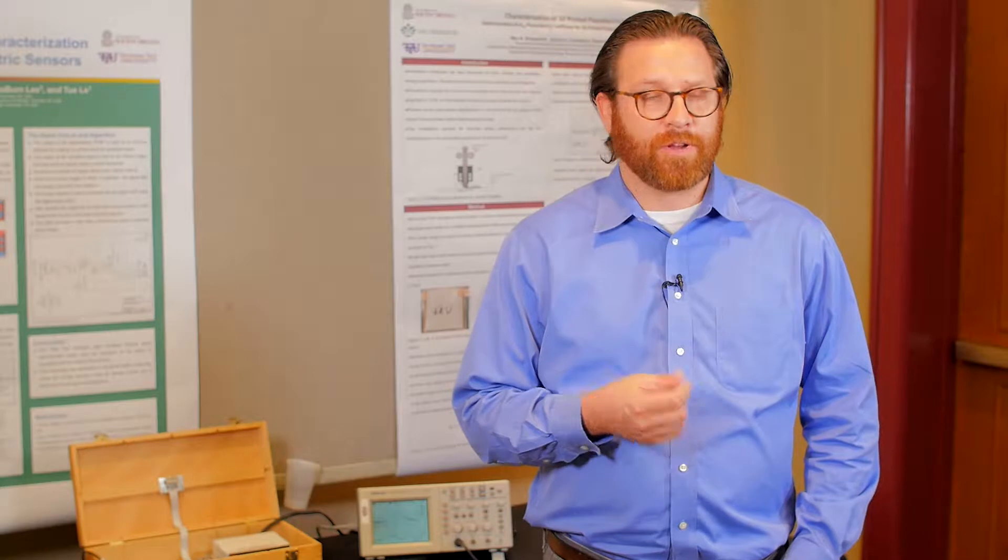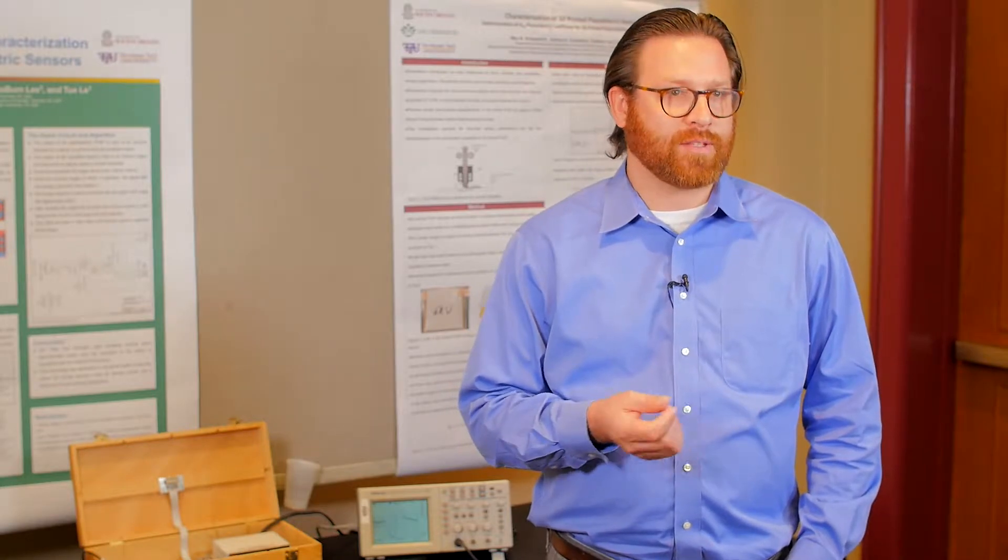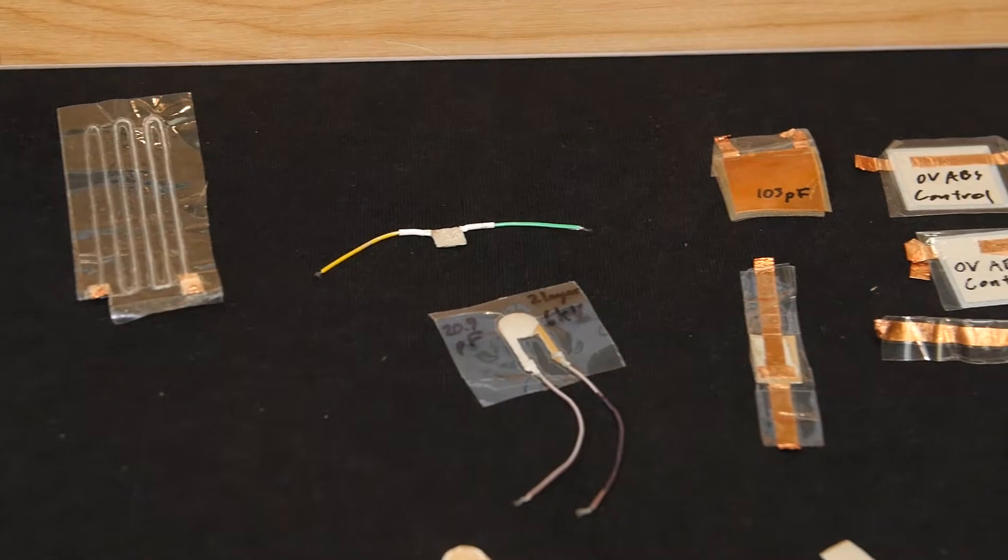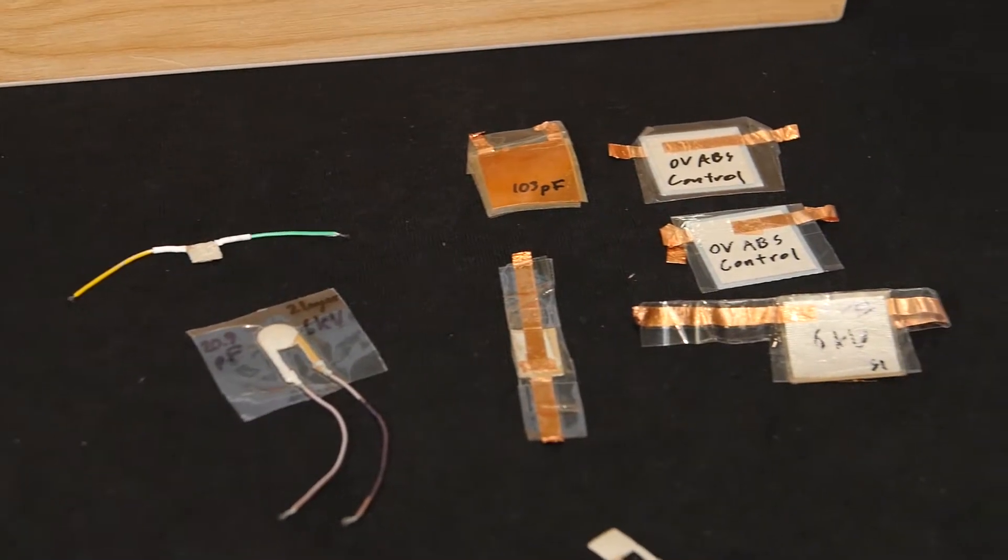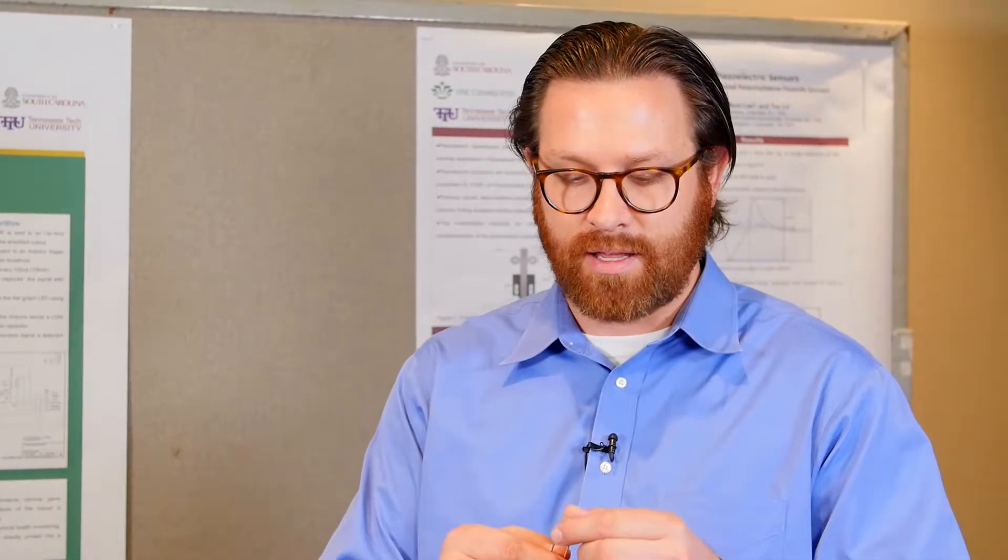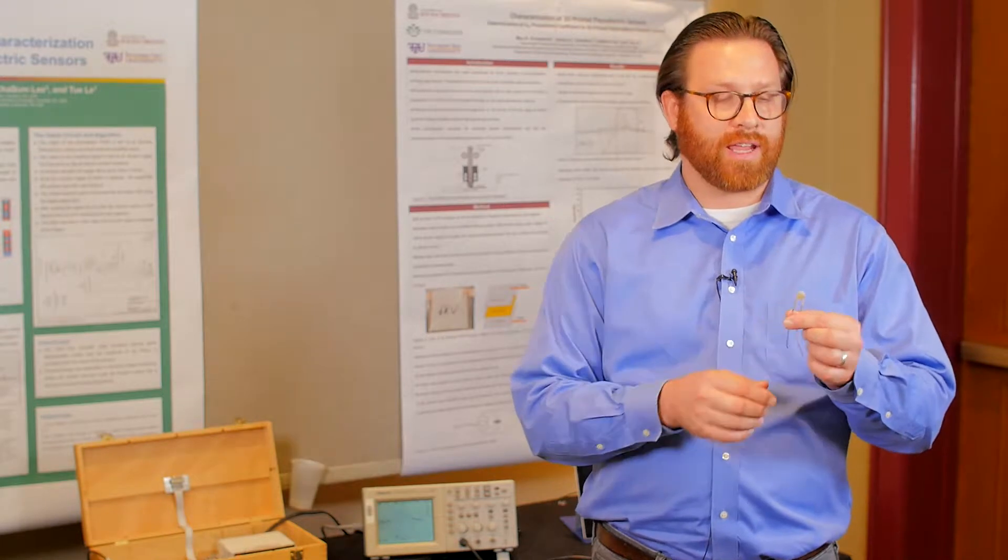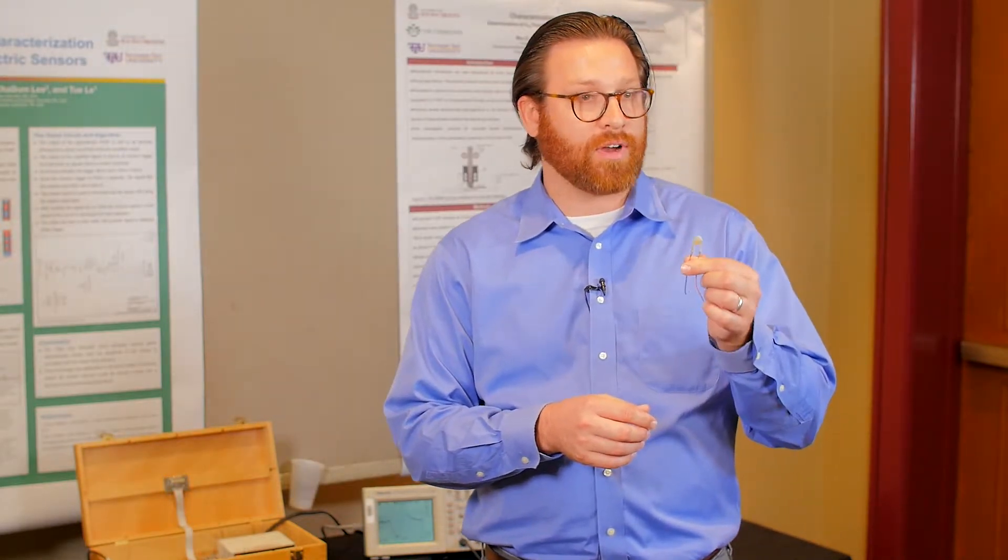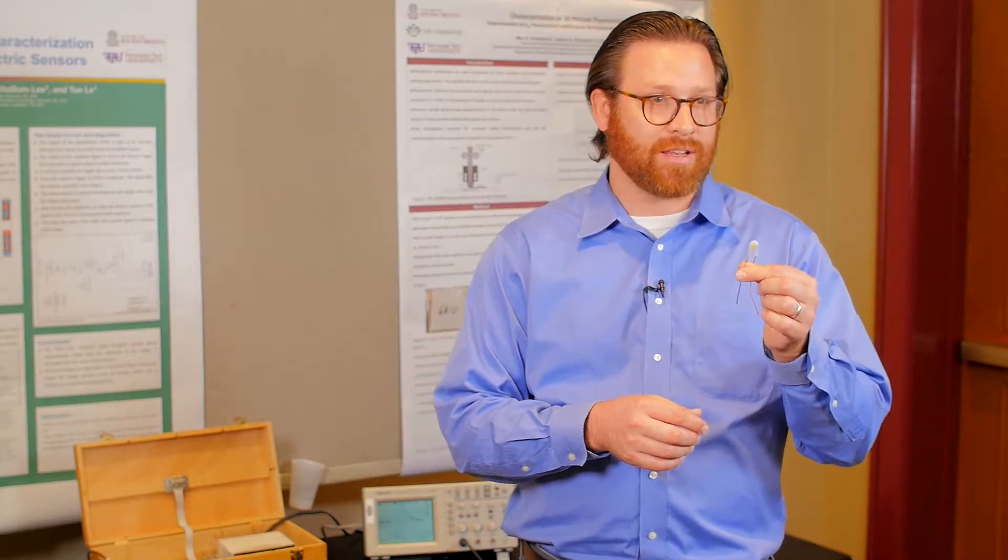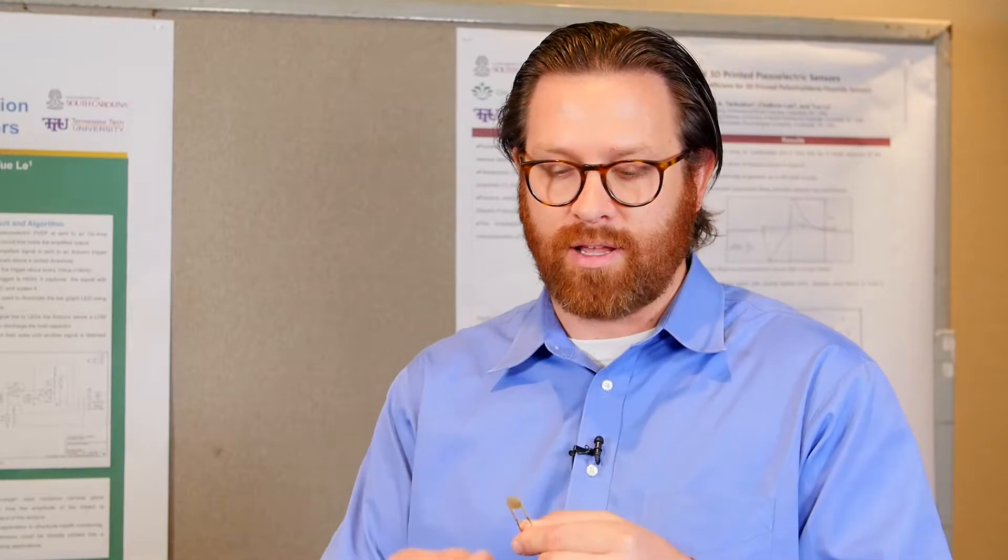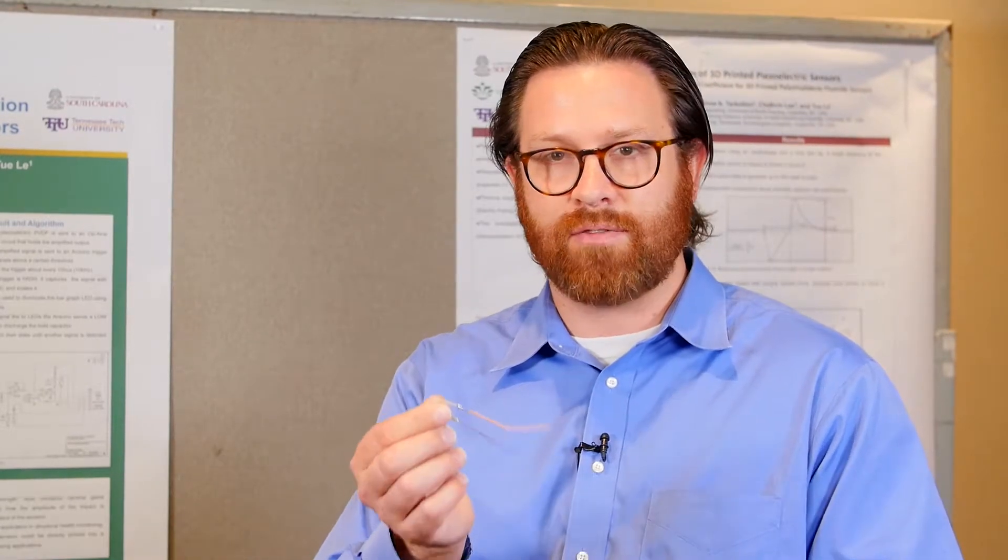We've figured out a new way of making piezoelectric plastic using a 3D printer, and today we're going to talk about some of these devices that we have printed. These are little pieces of piezoelectric plastic. It turns out that we can modify their crystalline morphology and their orientation during the printing process, so that when we're done printing them, you can push on them and get a voltage out.